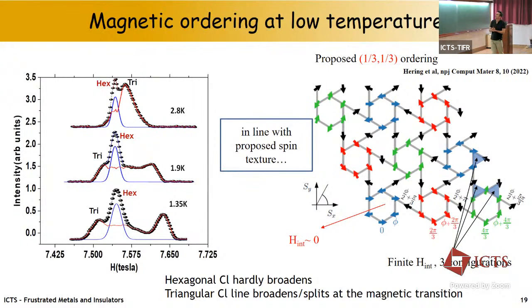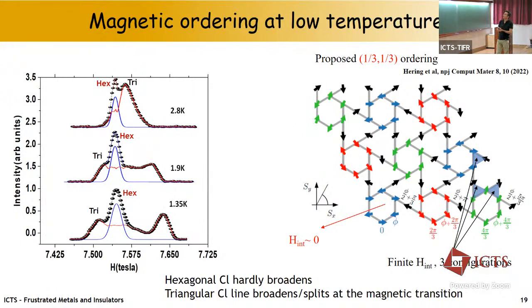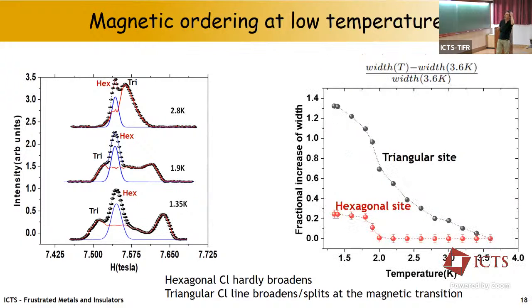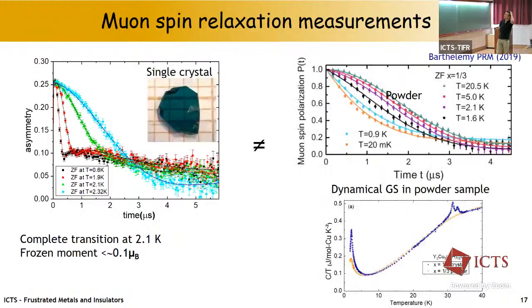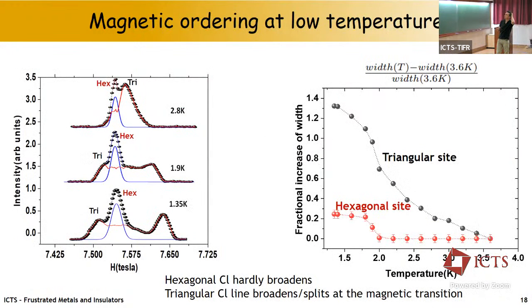Sorry, I didn't get it. This one? Or at higher temperature? Temperature dependence of the line width. At the magnetic... Yes, this is. So at the triangular site, the line width starts to increase below 3.6 K, which is quite different from the 2 K ordering in the hexagon or also the muSR data. So do you have any idea, or is this caused by the external field?